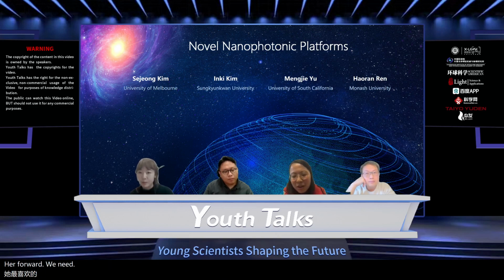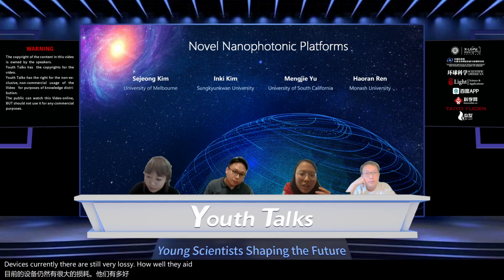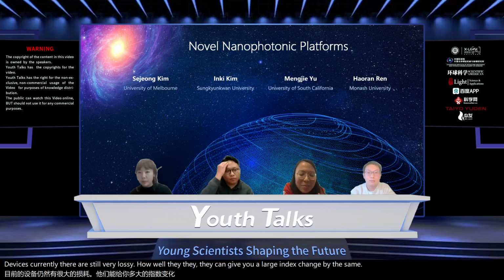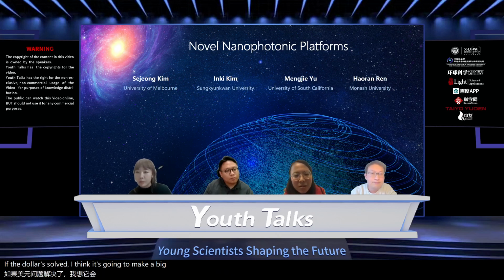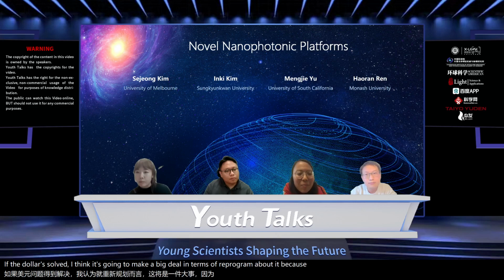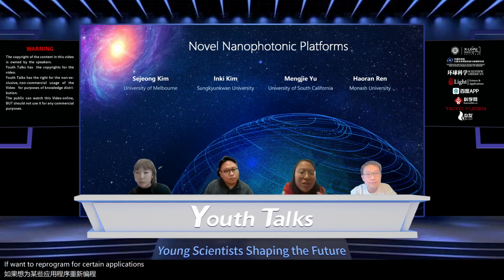But I still think we probably need to see more progress in the photonic memory devices. Currently they're still very lossy. They can give you a large index change, but at the same time, it also gives you a change of absorption. If that was solved, I think it's going to make a big deal in terms of reprogrammability. Because if you want to reprogram for certain applications, you don't need to reprogram many times, right? Or it's probably a very low frequency kind of change. So if this kind of reprogrammability doesn't consume energy, I think it's a big deal.